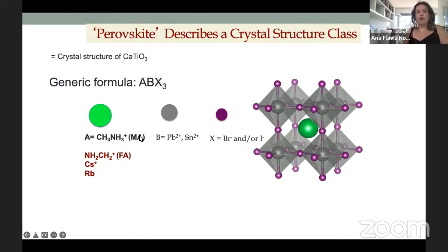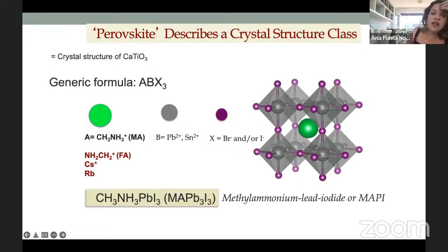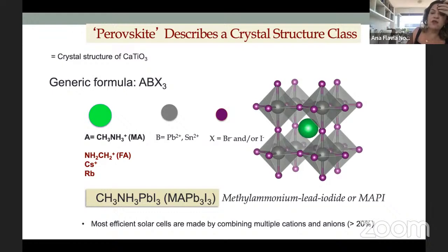For the halide perovskites, on the A site we can have both organic or inorganic cations, for instance methylammonium, formamidinium, cesium, rubidium, or a mixture of these cations. B, in most cases, is lead. There are many attempts to replace lead with tin, but the problem is that tin 2+ is very easy to oxidize to 4+, and then you lose the optoelectronic properties of the perovskite. And X, instead of oxygen as in calcium titanate, can be a halide or a mixture of halides. The most studied perovskite is methylammonium lead iodide, or MAPI, but you're going to see that the most efficient solar cells are made by combining different cations and different anions in the composition.